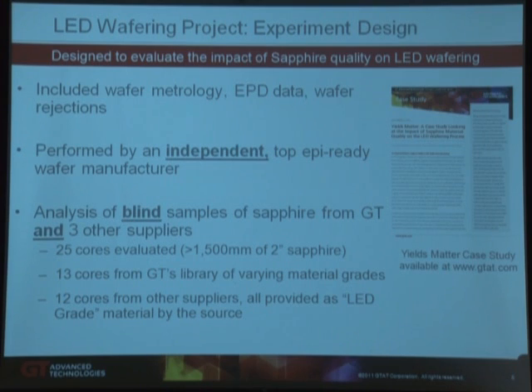Analysis of blind samples of sapphire from GT and 3 other suppliers and alternative sapphire growth technologies. In total, 25 cores were evaluated over 1,500 millimeters of 2-inch sapphire. 13 of the cores were from GT's library of varying material grades. 12 cores were from other suppliers, all provided as LED grade material by the originating source.